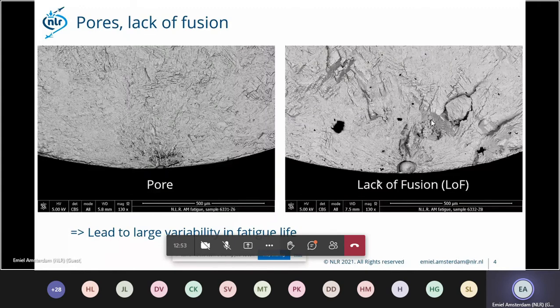And here you can see a lack of fusion defect, which is basically caused by a large metal droplet that falls on top of the laser powder bed fusion, the powder bed. Then the laser scans over this large droplet and cannot melt the powder below it, creating such a lack of fusion defect, and these are sites of crack initiation.